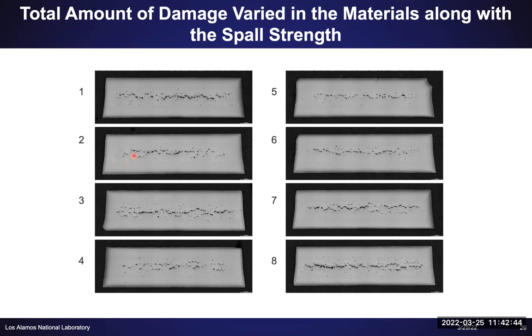But if you look at the morphology, the shape of the voids in a lot of these samples, as an example, if you look in sample 5, there are very small voids that are kind of separated from each other. But if you look in sample 7, those voids have started coalescing, they're joining together, and you're starting to see larger amounts of damage form. So in addition to differences in the stress required for void nucleation, we also noticed a difference in just the evolution of that damage over time. That's also important to us when we're looking at designing materials for specific applications.